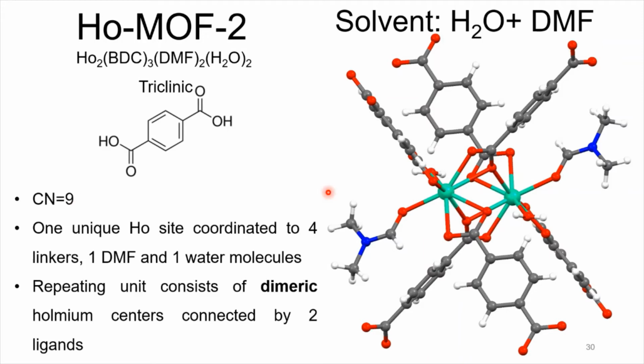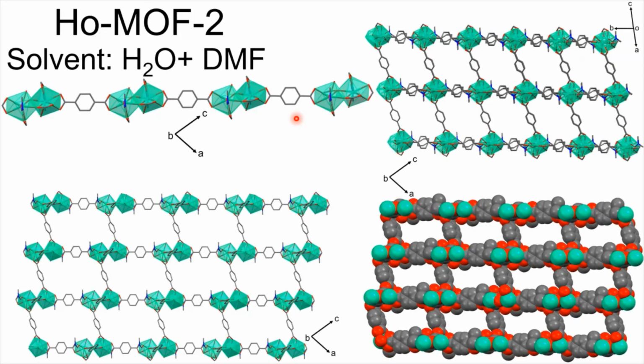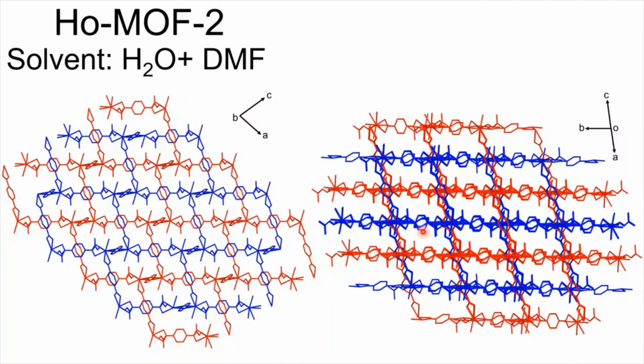Now we see DMF in the structure, but then again, there's a dimer at the center of this repeating unit. And you can see the dimer here more clearly, and it's the same. The dimers are connected by the terephthalic acid ligand in 1, 2, and 3 different directions. So you end up with this nice porous structure. The main problem or the main drawback with these ones is the pores are so big that you end up actually growing a second MOF inside those pores.